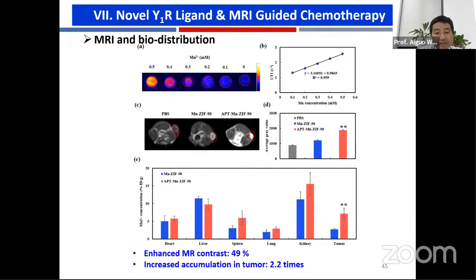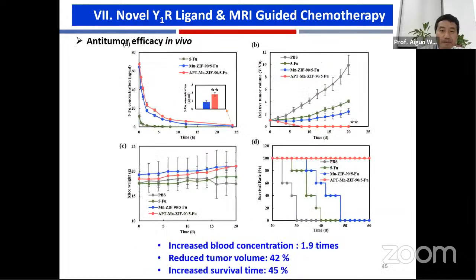And we found these nanoparticles mostly accumulated in the tumor area. It increased the accumulation in the tumor about 2.2 times compared to the control group. And we found this kind of nanosystem can increase the blood concentration about 1.9 times, reduce the tumor volume by 42%, and increase the survival time by 45%.